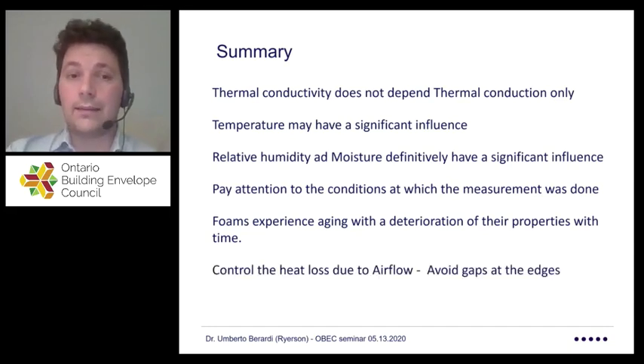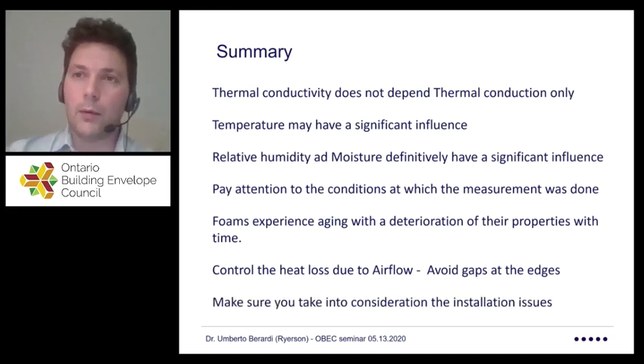We need actually to start getting a sense of how we control the airflow within the material, but also around the material. And we need to actually design details to avoid gaps and edge effects that could actually generate more convection. And then last but not least, we need to probably start getting a sense of how we install these products in the field. If you put products and you constantly penetrate with a lot of fastening, then at the end of the day, the thermal conductivity of any layer you use will be super far from the nominal value you may have obtained in a technical sheet.